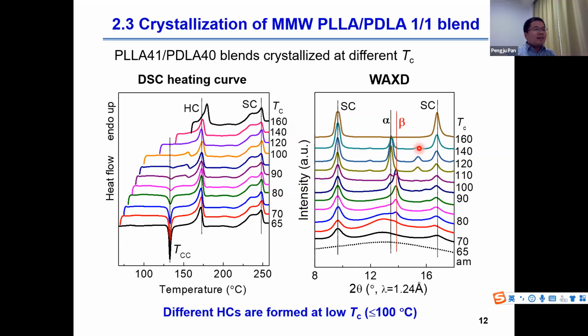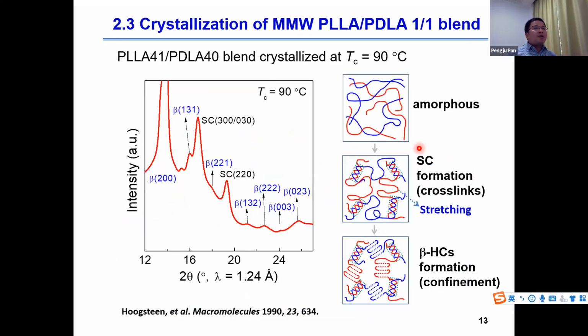To recognize this unique homocrystal structure, we enlarge the WAXD pattern and compare the XRD pattern with the reported polymorphs of PLA, including the alpha, beta, and gamma forms. We confirm this crystal belongs to the beta crystal. Beta crystal is one of the polymorphs of PLA, but it is quite difficult to obtain. We also propose the crystallization mechanism of the beta homocrystal.